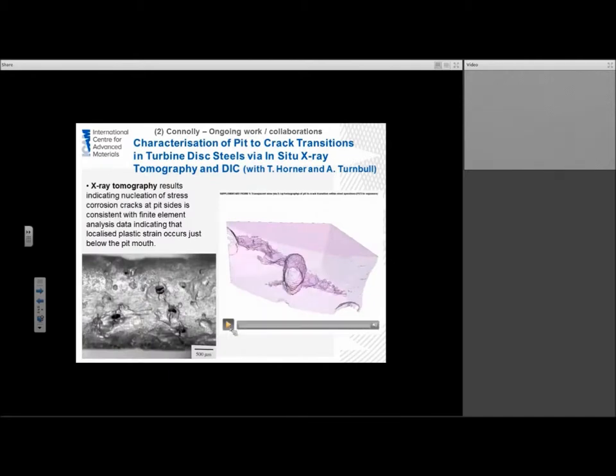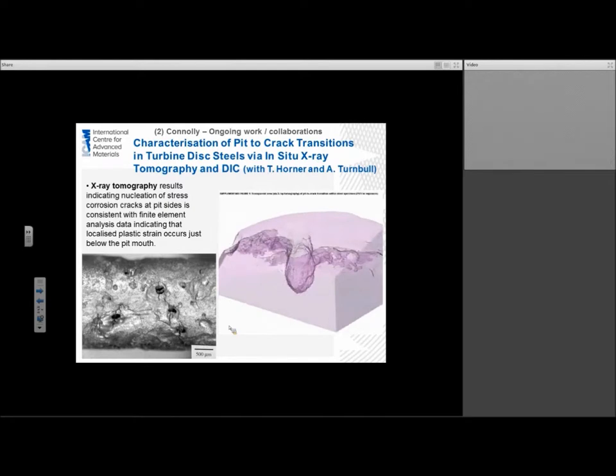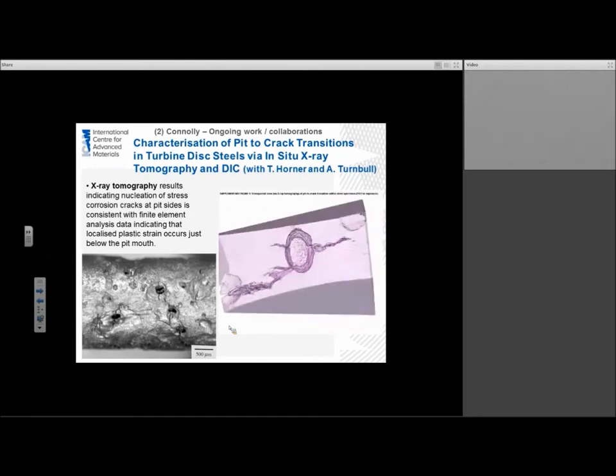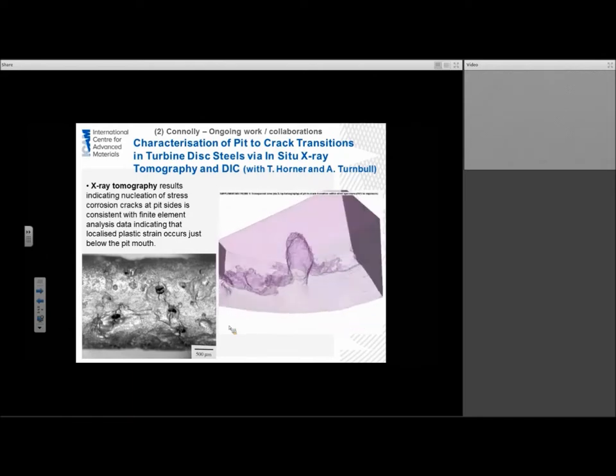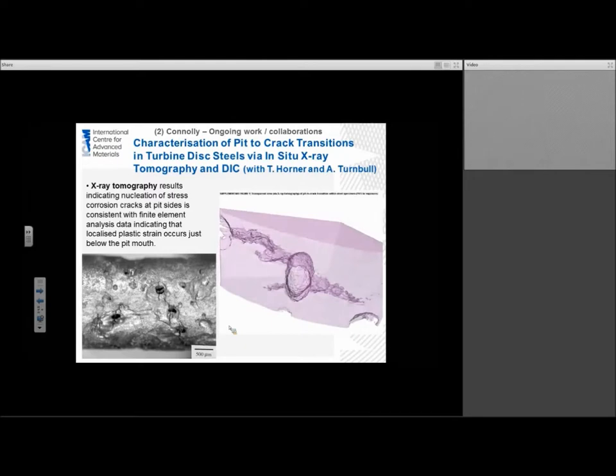With x-ray tomography, the movie that I'm going to play on the right of the screen is actually a reconstruction of the x-ray attenuation data from one of the experiments. This is the surface facing you of the metal and we can basically see into the metal. This being a very large pit and cracks emanating from each side. As we take a look at the reconstructed data, we see that the pit is much deeper than all the cracking events. This led us to believe that it is possible that we are getting initiation not at the deepest part of the pit, but at the pit mouth.